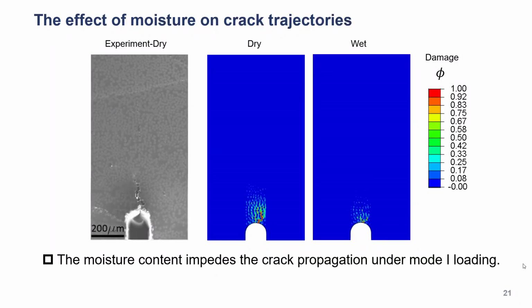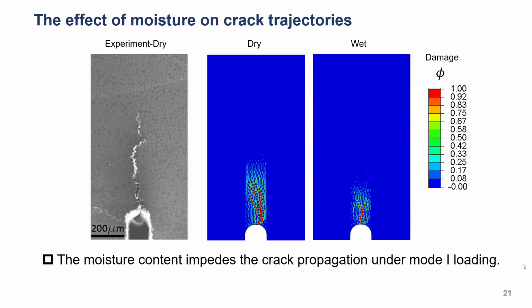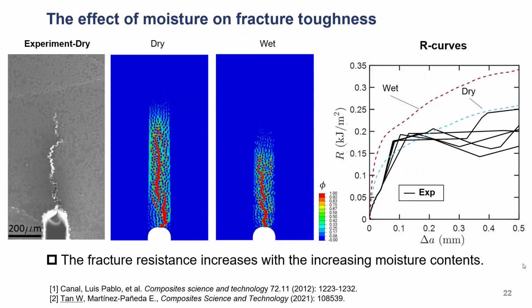Now this is the video showing the results. On the left, we have the experimental result where the crack grows. In the middle, you can see this is the dry case where the crack grows through the fiber matrix microstructures. On the right, this is the wet sample with very similar patterns, but if you look at them together, that's the final snapshot where you can see the same amount of displacement applied. For the wet sample, you have smaller crack extension. Looking at the R curve, you can see the wet sample has a higher fracture resistance.